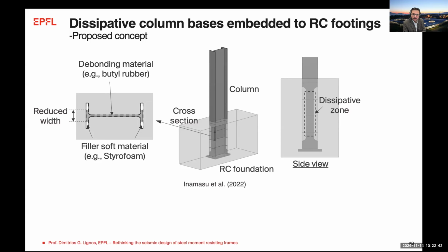My impression would be that rate dependency, for conventional systems like moment frames, will slightly impact maybe the onset of local buckling, because since you have more hardening, most likely buckling will be delayed a bit. But the overall behavior that we see should not be very, very different.